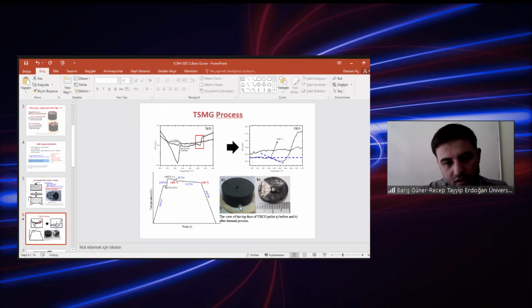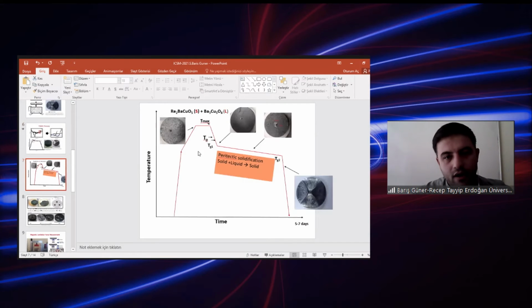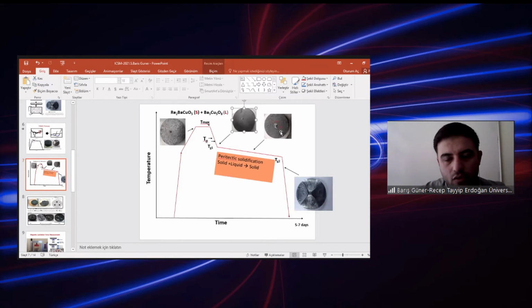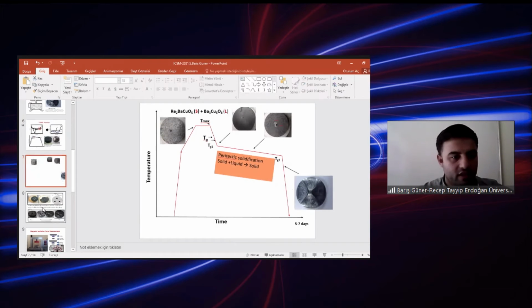This is the view of the top face of the YBCO pellet before the thermal process and after the thermal process, like that. This belongs to the top-seeded melt growth process. During Tmax, our samples look like that. At the peritectic temperature, there is a small growth. Can you see? This one is between TG1 and TG2, and this is after the thermal process.